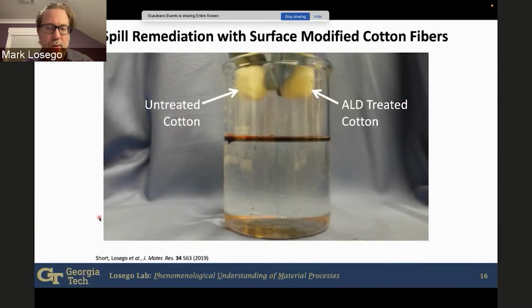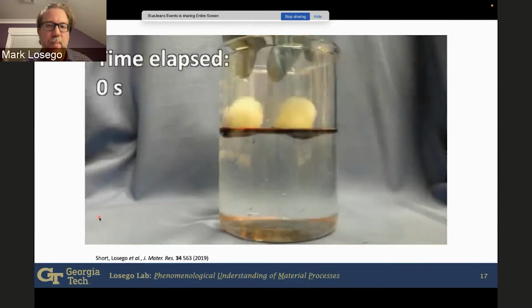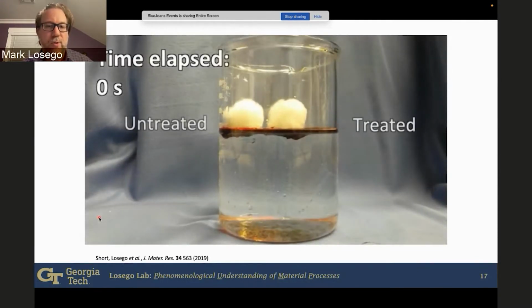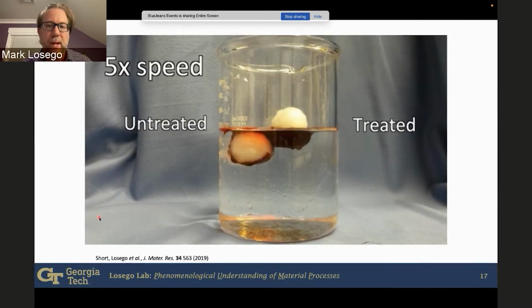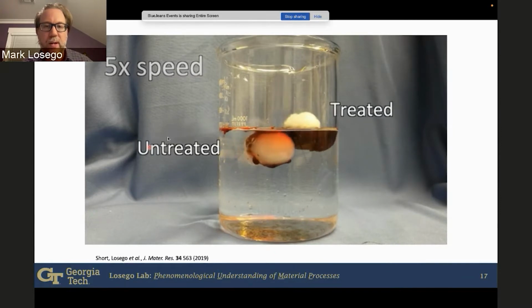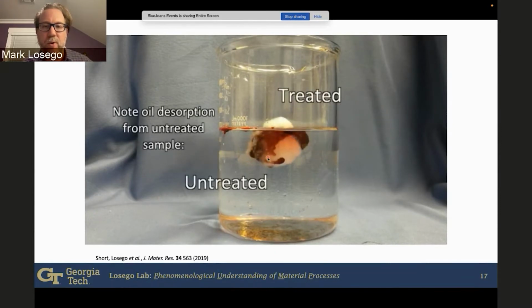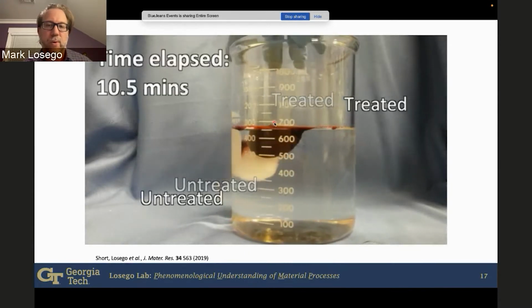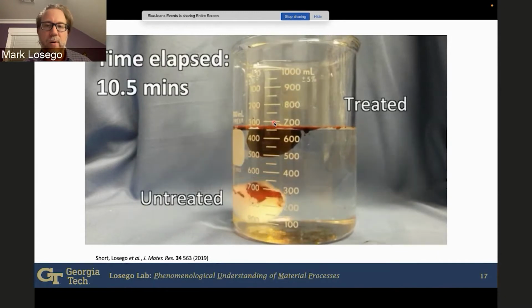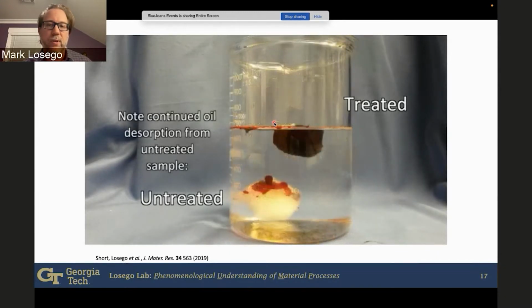they're also oleophilic. They actually soak up oil, and so we can use them for oil spill remediation. What you're seeing here is the untreated one. We do get some soaking of the oil, but over time it actually releases the oil, whereas our treated one will only soak up the oil and not soak up very much water at all. And we can use this for oil spill remediation purposes.